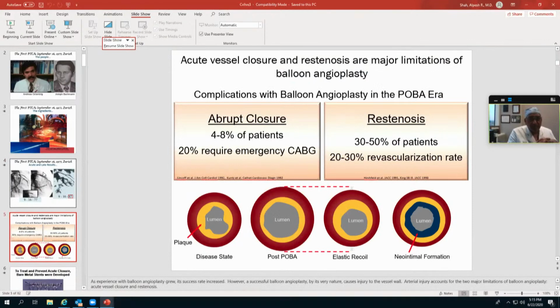But there are obviously varieties of reasons why we have reached today's sophistication of coronary stent design, and that's because of two problems. One was the abrupt closure problem, which happened after balloon angioplasty in about 4 to 8% of our patients. And as you can imagine, one-fifth required emergency bypass surgery. But the second problem was obviously restenosis, which happened in 30 to 50% of those patients. And out of them, 20 to 30% actually had to have revascularization.